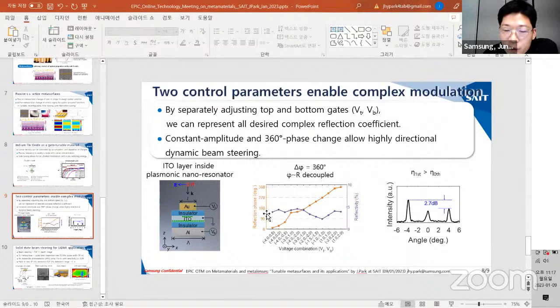Actually, the field of view or field of illumination is dependent on the pixel size of this unit cell. So basically, in our structure, it turned out the pixel pitch was around 400 nanometer. So in theory, this field of illumination can extend plus minus 90 degrees, actually. But in order to make some proof of concept demonstration, we combined multiple antennas into a single big giant cell with the pitch of 5 micron. So that's why we came up with a small field of illumination. But in principle, we can extend it a lot. Yeah. Okay. Interesting. Thank you, Olaf.